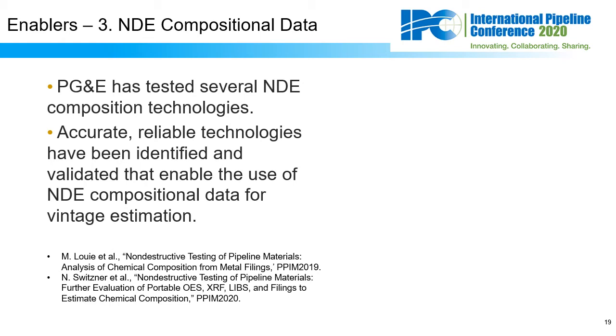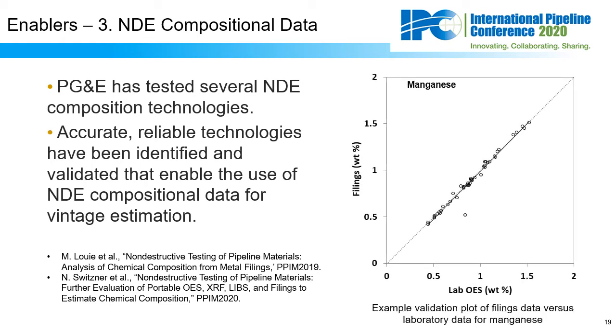For composition, PG&E has tested a variety of NDE compositional detection techniques and found several technologies quite capable of producing accurate results, such as what you see here for the element manganese. So this example validation plot shows that the NDE composition method of filings collection and measurement of manganese correlated very well with the laboratory measurements. Similar validation plots have been made for a number of important elements and published by PG&E in the publications shown at the bottom of this slide.